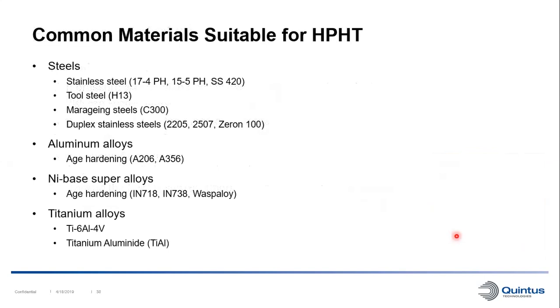And here are some examples of common materials suitable for high pressure heat treatment. So we have our steels, which are stainless steels. We can have the 17-4 PH precipitation hardening steel. We have stainless steel 420, martensitic hardening steel. We have tool steels, maraging steels, duplex stainless steels. Also aluminum alloys, they're typically age hardening, can be produced. The nickel-based superalloys are common for age hardening. For example, Inconel 718, Inconel 738, and Waspaloy. And then we have titanium alloys such as Ti64 and also intermetallic titanium aluminide.